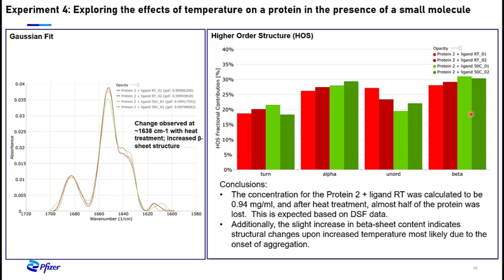Based on the quantitation data from this experiment, which is not shown, it was evident that after heating the protein to 50 degrees, we lost about half of it, which is no surprise since our 50 degrees is approaching our Tm and aggregation has begun. The slight increase in the beta sheet content indicates structural changes upon increased temperature, most likely, again, due to aggregation.